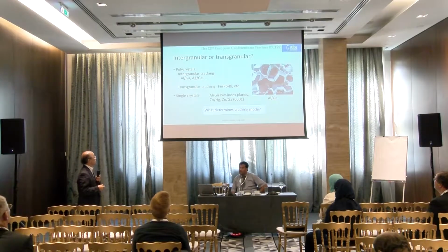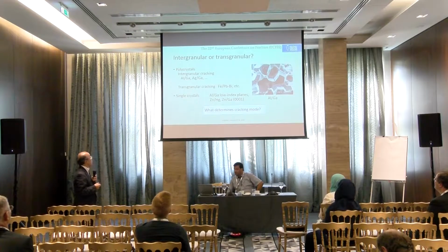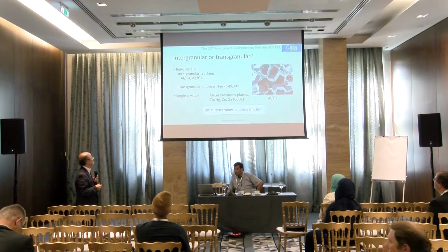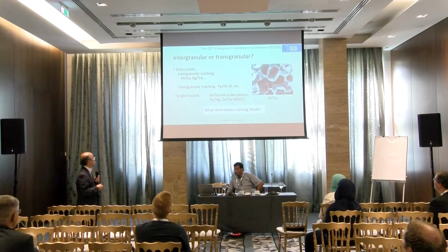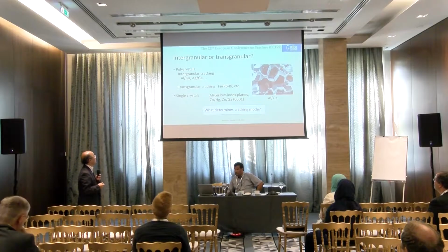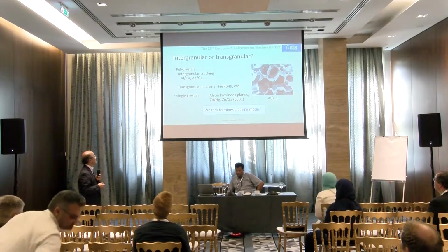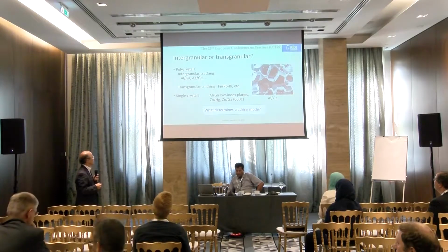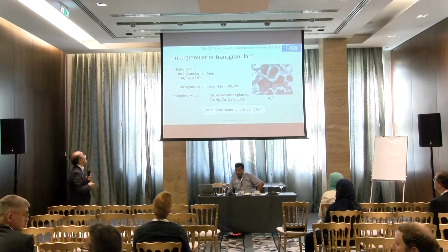If the liquid metal has an effect only in the grain boundaries, a single crystal should not be affected by the liquid metal. But actually, aluminum single crystal is embrittled by liquid gallium, and single crystal zinc is embrittled by mercury, and so on.